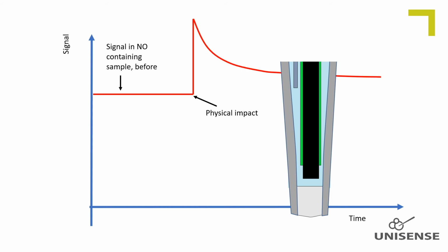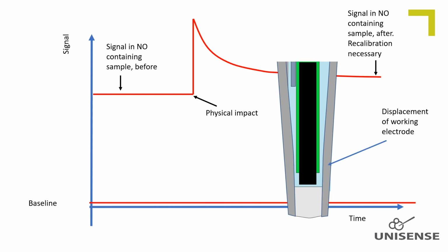Physical impact to the sensor can, besides destroying the sensor, change the sensitivity and thereby the calibration curve of a nitric oxide microsensor. The working electrode connects to the amperometer via a thin, flexible glass-covered platinum wire. Physical impact, which shocks the internal components, can induce a displacement of the working electrode position relative to the membrane and thereby change the sensitivity. Typically, such impact will induce a sudden signal peak, followed by a stabilization time. But the sensitivity might not return to the original sensitivity caused by a displacement of the working electrode position. The baseline is normally not affected.